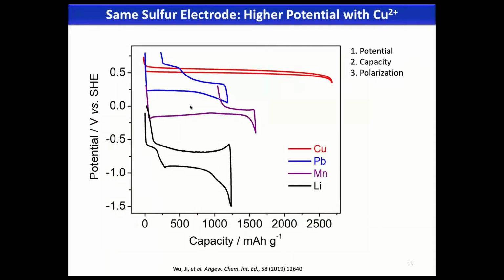Quite interesting. And recently, we used the same sulfur electrode. We actually tested the storage of different charge carriers, including copper. This is quite interesting. If you see, the potential is way bigger than lithium. It's higher than 1.5 volts for the same sulfur electrode, which is nanoparticles of sulfur infiltrated in the porous carbon. So sulfur need not have this mediocre voltage. It can have a super nice voltage, which is relatively the same as lithium iron phosphate. And of course, the capacity is also high. But here we didn't count the mass of lithium ions or copper ions. So the polarization is very small. I'm going to explain that later.